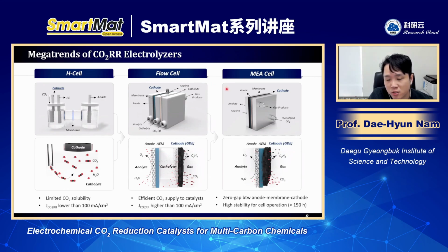The common point of them is that they all use a GDE-based cathode. GDE means gas diffusion electrode. The major difference between this H cell and GDE-based electrolyzers is how we supply CO2 to the catalyst. For example, in the case of the flow cell and MEA cell, because we use a GDE, which has a porous structure, we can directly supply CO2 to the catalyst from the backside of this electrode. So by flowing CO2 directly to this part, we can supply CO2 more efficiently. And this enables us to overcome the CO2 mass transport limitation.